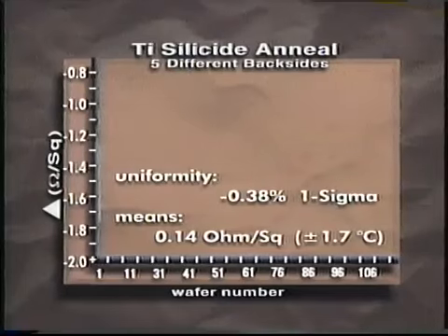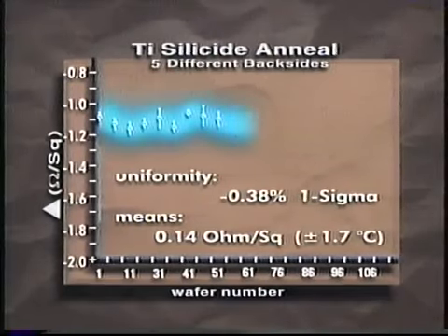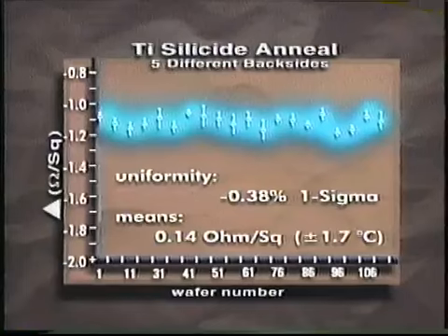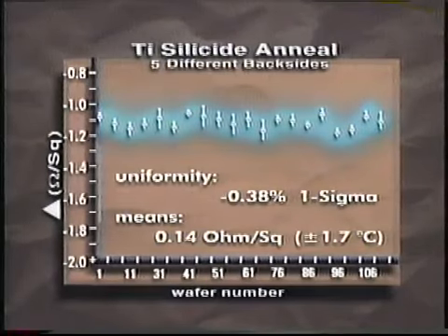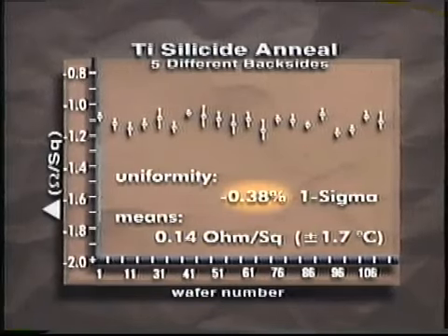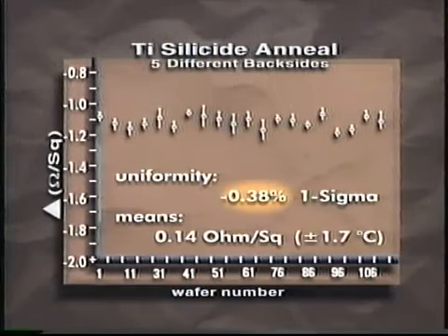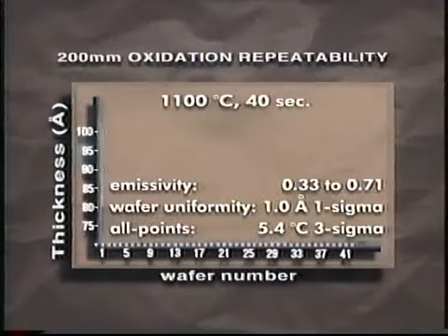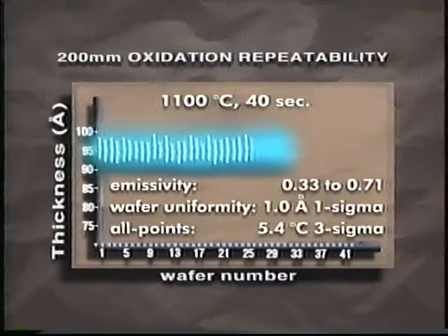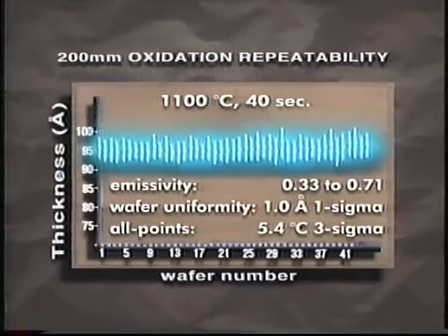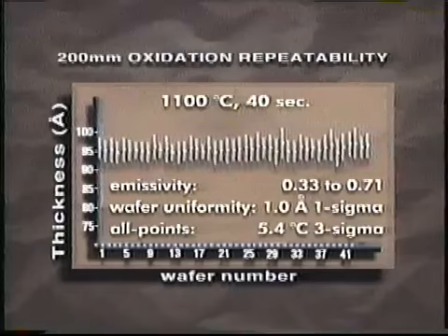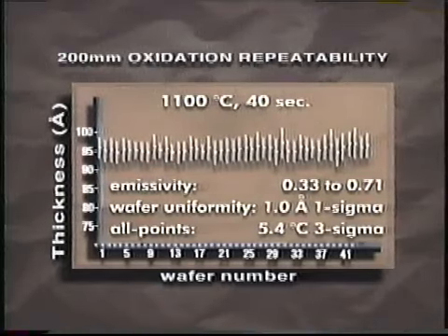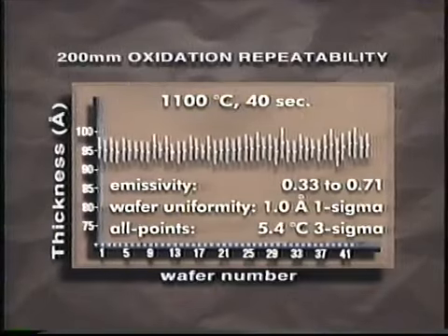Annealing of titanium silicide films improves with the RTP Centura in process uniformity and repeatability. Added non-uniformity is controlled to less than 1%, independent of wafer backside films. Creation of thin film oxides for use as the gate oxide was not previously achievable with RTP technology. However, with the Applied Materials RTP chamber, oxide uniformities of better than 1% are achievable.